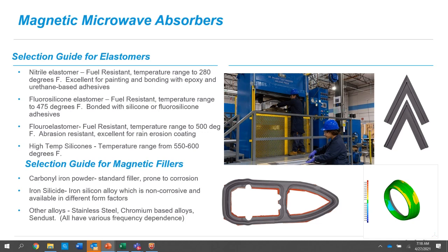Fluoroelastomers are a little different. That's things like Viton. They're also fuel resistant, got a good temperature range as well, but then also a lot tougher than the fluorosilicones, which are softer, and they've got good abrasion resistance. So if you have a rain erosion issue or an abrasion issue, the Viton is really a good all-around material. And then I bring up silicones only because we have standard silicones, but we're now working on silicones that can get up to 600 degrees Fahrenheit.